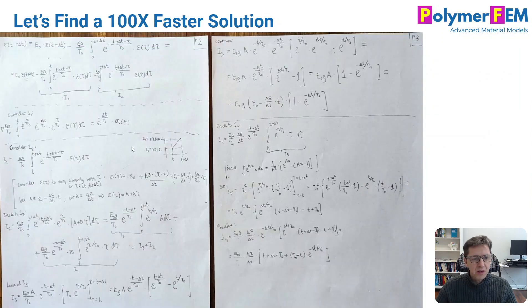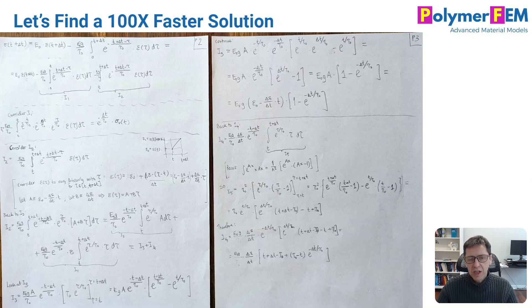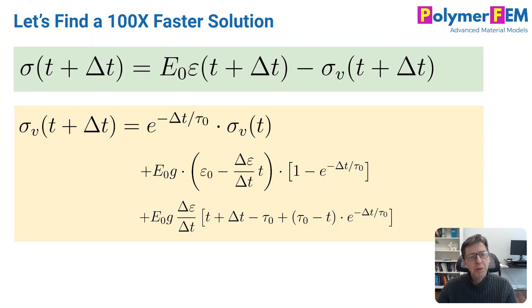We can do a little bit of math, which I did. Here's a little bit of math to prove to you that I actually calculated this. I derived this from scratch. Here are my equations. And it's pretty easy to do. Once you go through it, just do it step by step. That's a great exercise, actually. If you like math and you want to do this, go for it and see if you can come up with the same equations that I did. And here's the answer. So the stress at t plus delta t is equal to the instantaneous response minus some kind of viscous response. And this is how you calculate the viscous response: it's these three terms that you need to calculate. So to actually perform this calculation, you need to keep track of sigma v, which is a state variable. To go from t to t plus delta t, we need to know the viscous stress at each point in time, so we can use that in this calculation. But there are no other complications here. This is a very straightforward, quick calculation to perform.